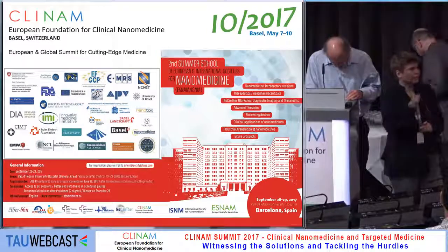Yes, actually, the particles were dissolved, I think, in PBS. However, the main problem was we are starting with a powder, and in the beginning we had really single nanoparticles, which very quickly, due to the high concentration, started not perhaps really to aggregate, but to agglomerate.